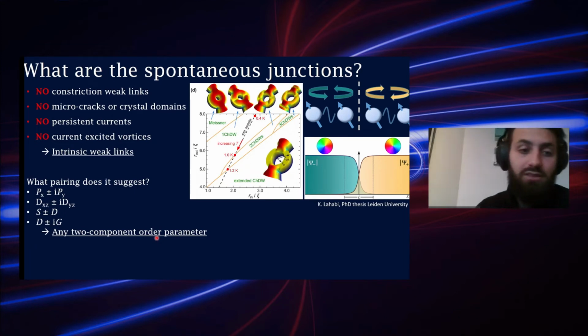That doesn't really matter, so in any two-component order parameter, this can happen. And our collaborators in Antwerp actually carried out time-dependent Ginzburg-Landau calculations and found that in the size of microstructures that we are using, two chiral domain walls could be stable in either arm of the ring, explaining the results.